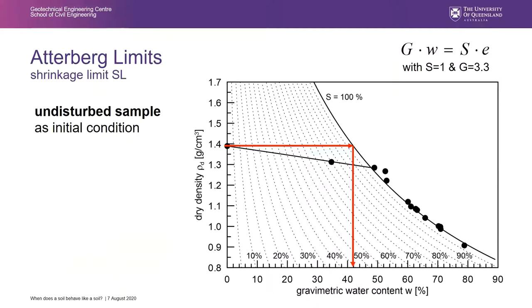So this is now an example of such a test. I have to say that in this case we used an undisturbed sample with a good reason, which I will present a bit later. So an undisturbed sample was used as the initial condition. This is the 100% saturation line, calculated with the equation I've shown before and a specific gravity of 3.3, which is very high. What is normally done is that we look at the density at the very end, at 0% water content, and we use that point on this line to determine the shrinkage limit. If we had done this test under remolded conditions, the shrinkage limit would not have been much smaller. It's a bit smaller, maybe 38, from what I've seen in another result.